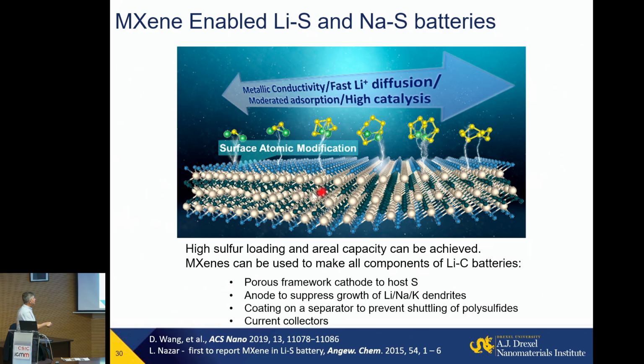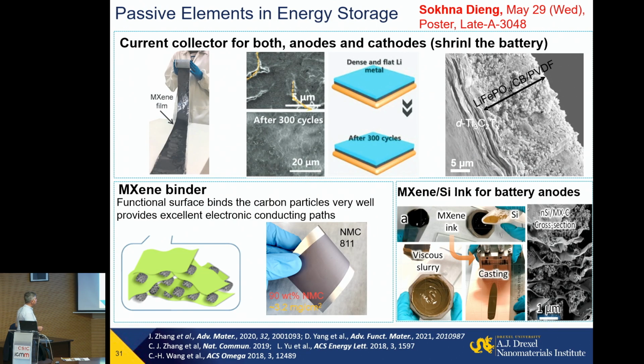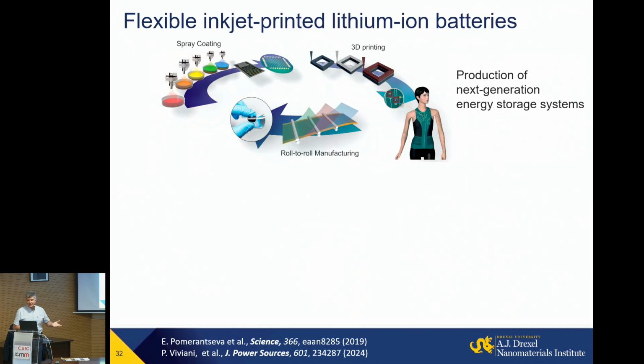And again, sulfur has very low conductivity. It's dielectric basically. Metallically conducting MXene in the cathode can help to develop a conductive scaffold for those batteries. I already mentioned the possibility of using current collectors, but what is important? Lithium grows parallel to the surface without forming dendrites, so we can make metal batteries: lithium, sodium, potassium metal batteries. And we can use it also as a current collector on the cathode side, for example, with LFP, or as a conductive additive to NMC, LFP, silicon, carbon, for example glassy carbon for sodium ion batteries, many other things.